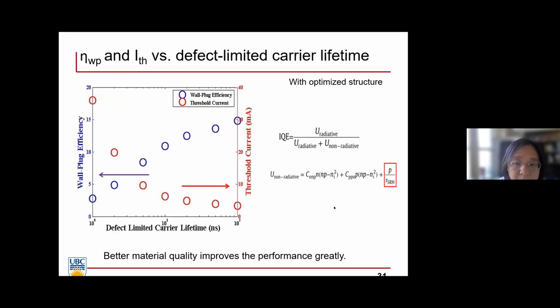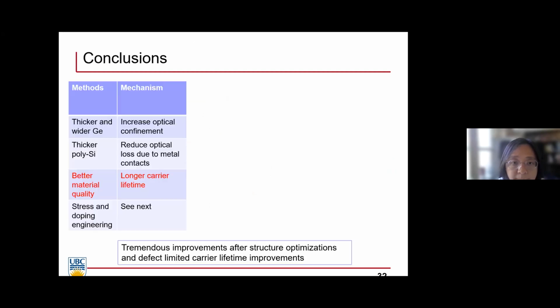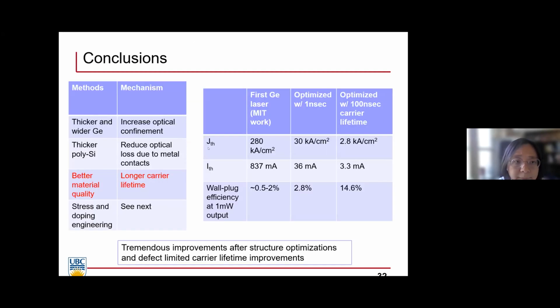I'll skip some optimization curves; you can find them in our publications. Really, the conclusion is that if we use thicker and wider germanium, that will increase the optical confinement. Thicker polysilicon will reduce the optical loss due to metal contacts. And really the key is to have better material quality with longer minority carrier lifetime. And we can also use stress and doping engineering.